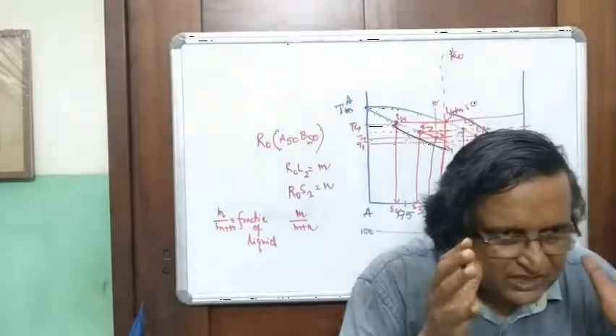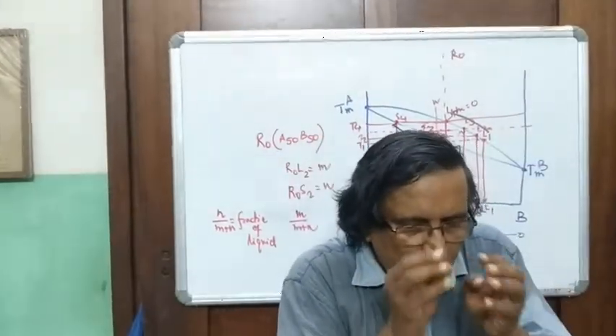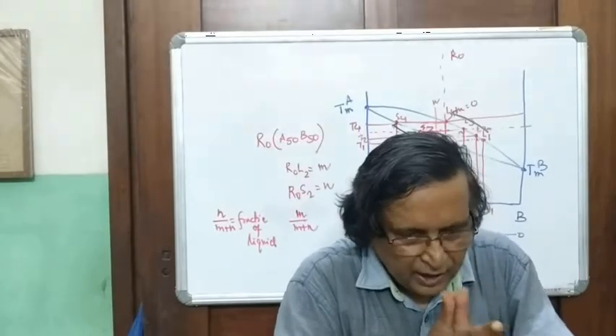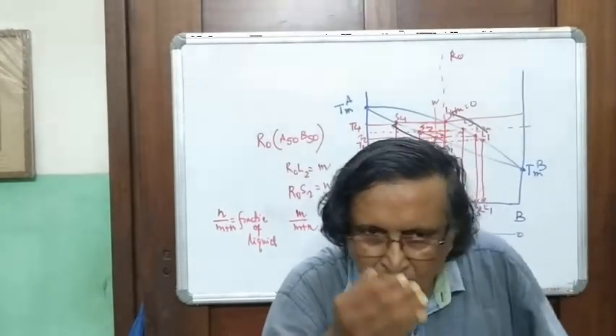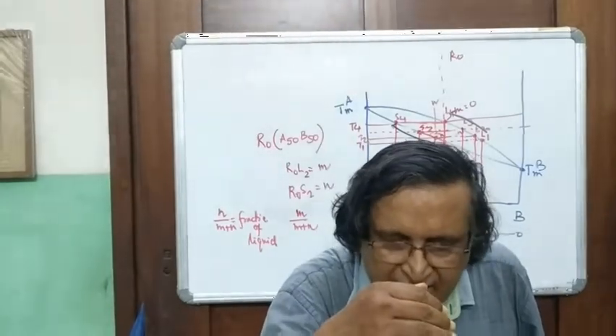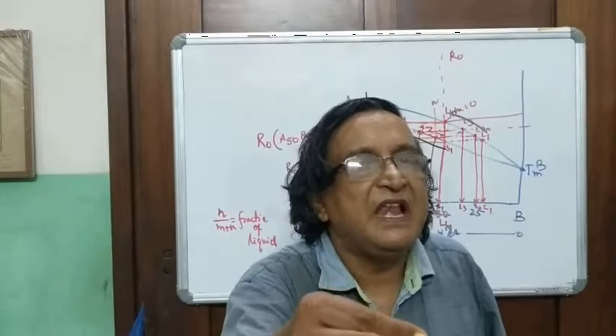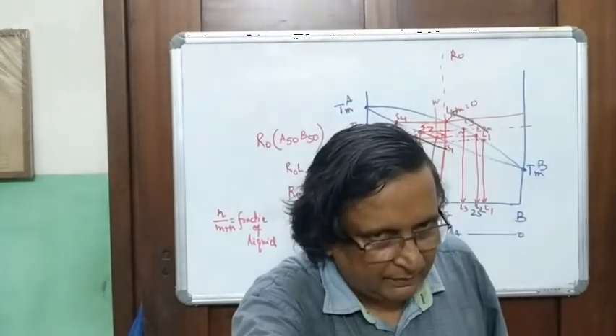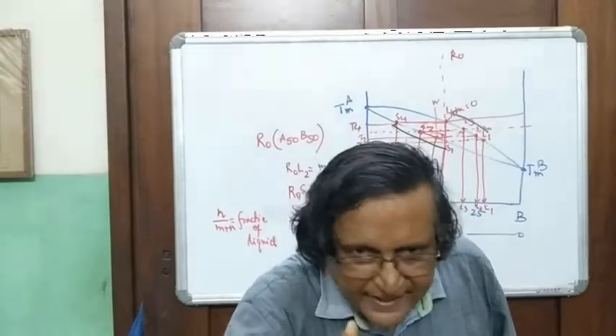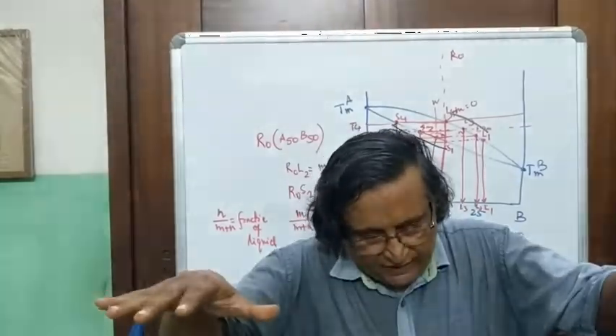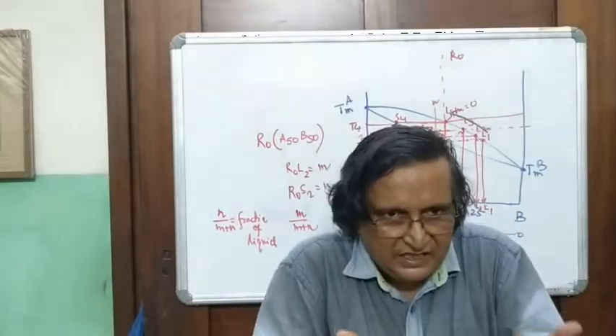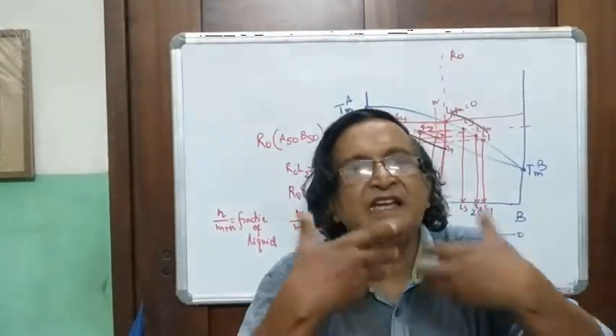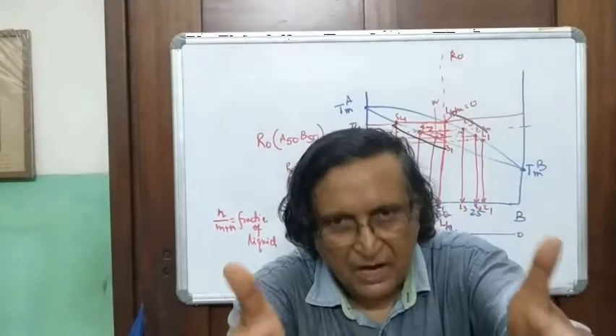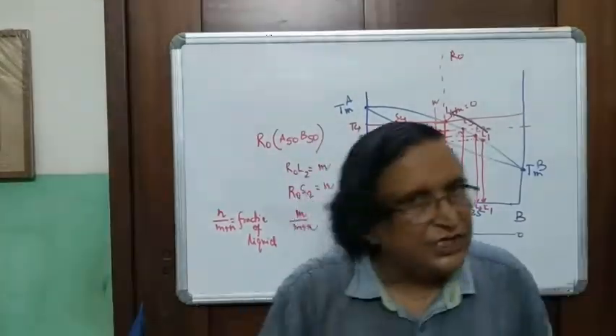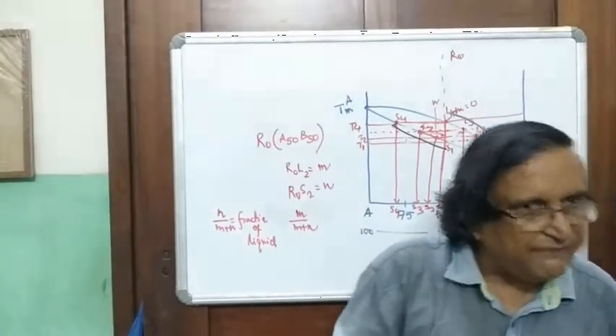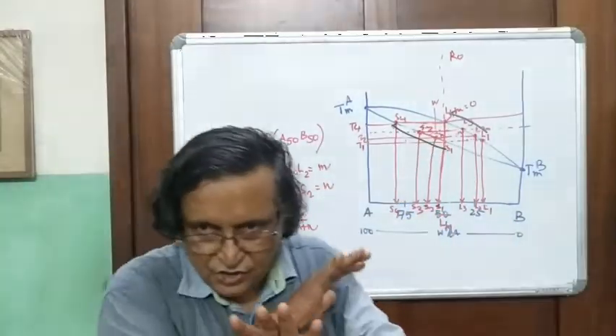Now there is an important problem here which I must tell you, and you remember this. Remember, in the simple eutectic system, when we were melting, for low degrees of melting, the more heat you gave, you produced more melting. So there was thermal buffering. The temperature did not rise. As you gave heat, that was transferred into latent heat of fusion and material passed into melt. But the temperature did not change. So that caused thermal buffering. Here, there is no thermal buffering.